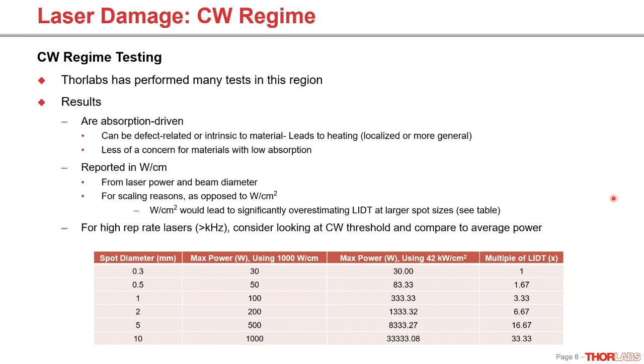For example, something like germanium will undergo some heating as you pass a laser through it, just because it has a decently high coefficient of extinction. So CW damage is less of a concern in materials with lower absorption, but it is typically something you should be aware of, because very few things have essentially no absorption. We try and drive it low, but it's always there. These results are reported in watts per centimeter, and that's from laser power and beam diameter. This isn't in watts per centimeter squared, which many of us are used to looking at.